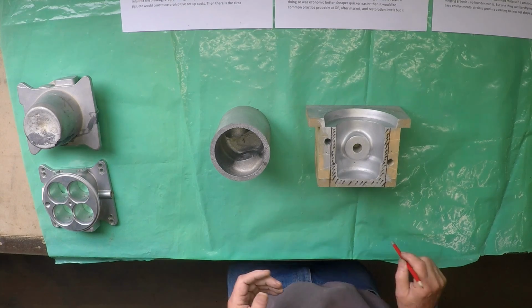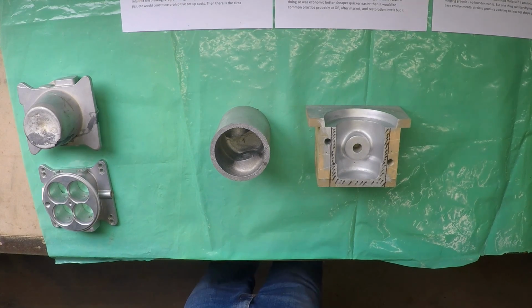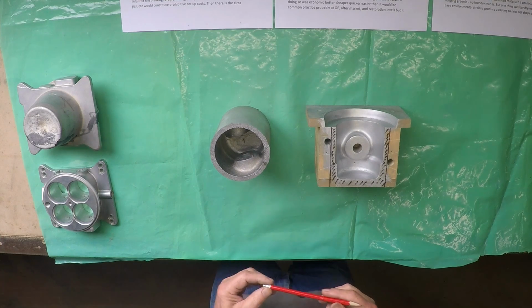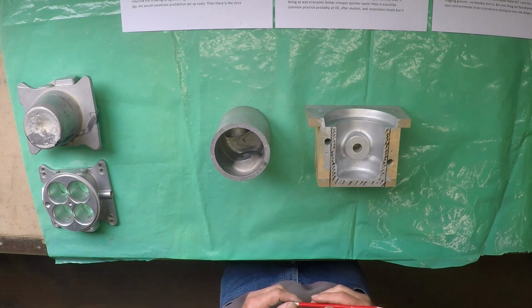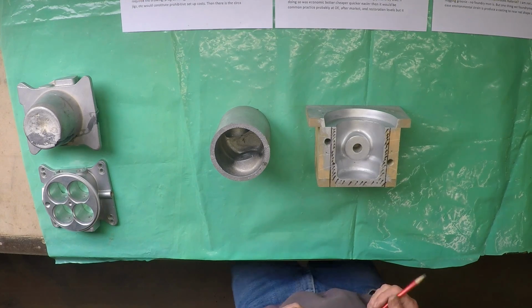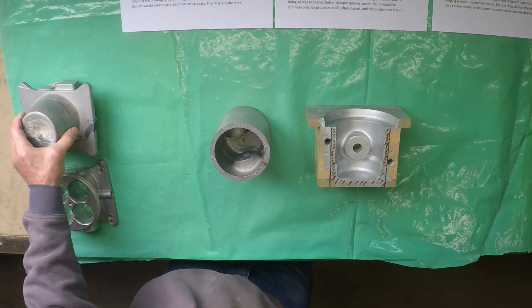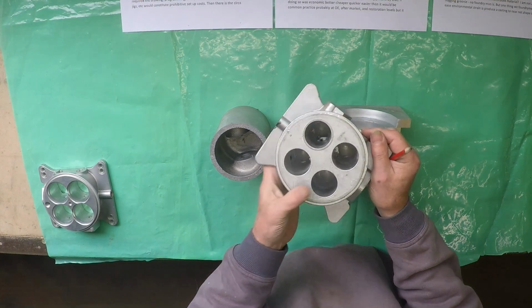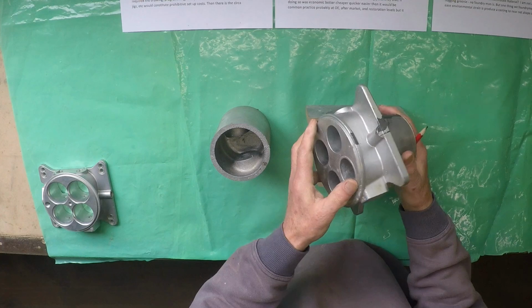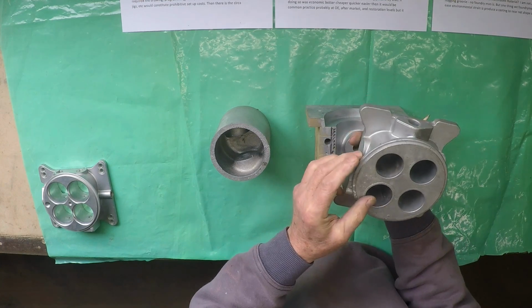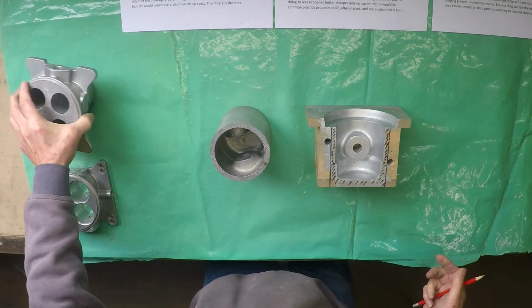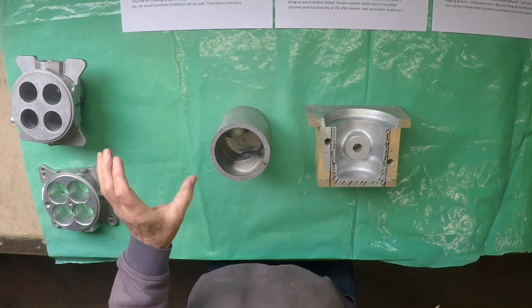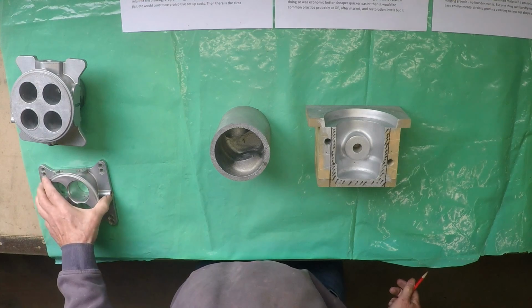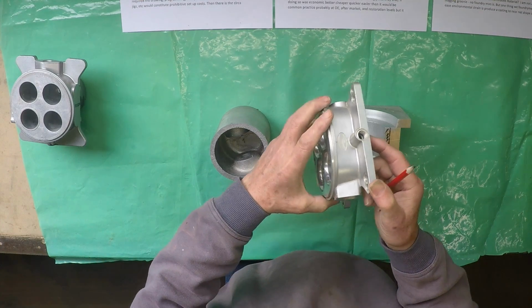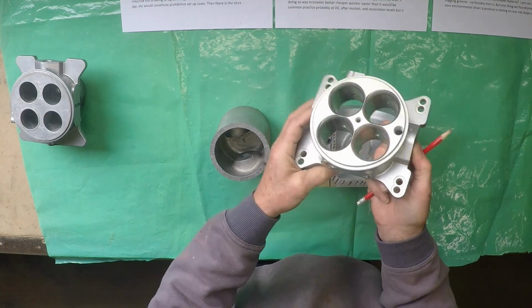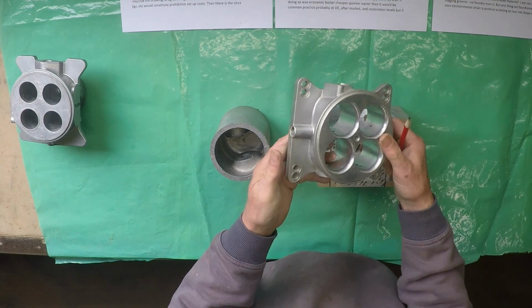Now, while casting is my thing, I am not totally biased against CNC. I own a CNC mill, and I have used it to produce things rather like the complicated 9-piece die for this particular casting. It's a 4-barrel throttle body. This one's been lying around for a while, so it's got a bit dirty now. And this is an interesting case in point, because we've used CNC machining to produce an iron die. Then we've used the iron die to produce quite a nice looking casting. And then we've gone back to the CNC to finish machine that casting off.